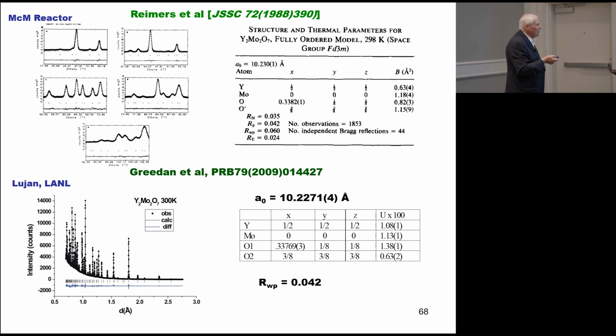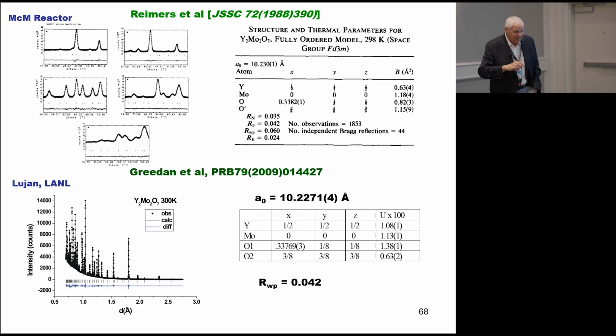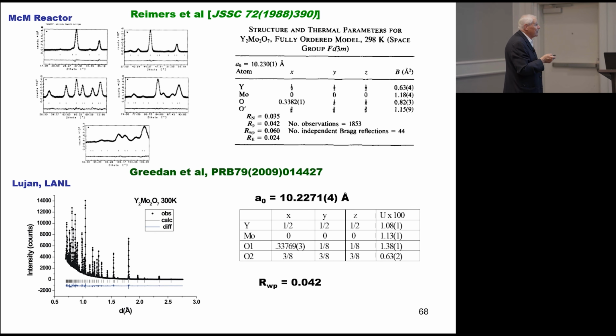So we look for disorder in the average structure of the diffraction patterns. These were data originally taken by Jan Reimers and analyzed. We analyzed every possible substitutional disorder, displacement of atoms here and there, and none of them worked better than the average structure. We did the same when slightly higher resolution data became available at the Lujan Center. We did the same thing, and the average structures refined perfectly to well-ordered pyrochlores.